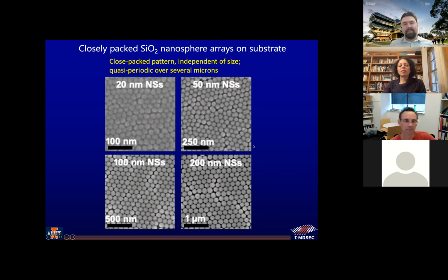Okay. And so we make, as I'll show, our devices typically about 1 to 3 microns. And so we might have 4 or 5 domains in there. You can actually see Fourier transform peaks on these, which means that it's still structured enough that you're getting the effects of crystallinity, but not perfectly.